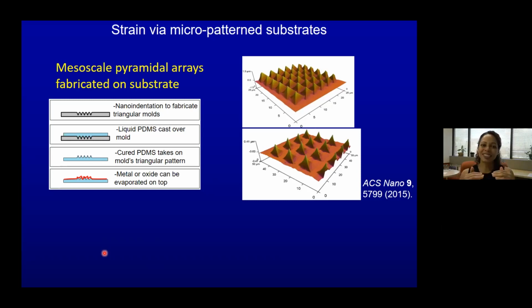So what this student did is he took just a piece of plastic and made nano indentations in it. There's a box-like machine called a nano indenter, and you press it down. As you can imagine, it makes pock marks where you want across the sample. He made a couple micron in size indentations, and then he poured PDMS, a rubbery material, and molded it into these indentations and peeled it off. So then what we had were these indentations on the surface of the mold. And then we could evaporate metal or an oxide to make it more rigid, so it wouldn't just bend.